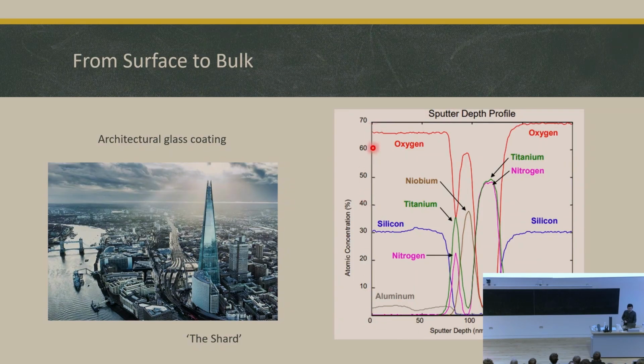Before we start etching, we can see there are 3 elements: oxygen, silicon, and aluminum. This kind of aluminum doped silicon glass protects the glass from wear and tear and extends its longevity. If we start etching a little bit, just over 50 nanometers, we start seeing only titanium, nitrogen, and oxygen left. This layer, very thin, maybe 5 to 10 nanometers, is a low emissivity material coated on the glass. It is transparent to visible light, but blocks a significant amount of heat.